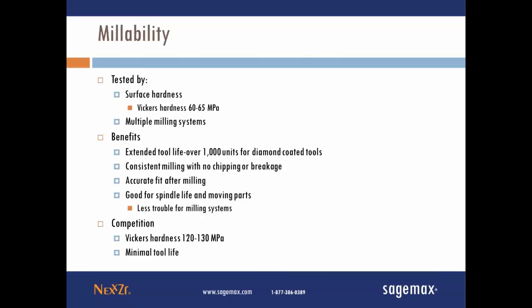So millability is actually something that is also very important to us. Dan had mentioned surface hardness of some of our competitors, particularly if the product has been uniaxially pressed. For a uniaxial press material, we're looking at a surface hardness of about 120 to 130 megapascals. With Sagemax NexxZr T material, we're only looking at about 60 to 65 megapascals. So what that means is, of course, longer spindle life, longer tool life. Not only for diamond coating tools is it increasing the longevity, but also for carbide tools. We're seeing our customers get roughly double the tool life of carbides.